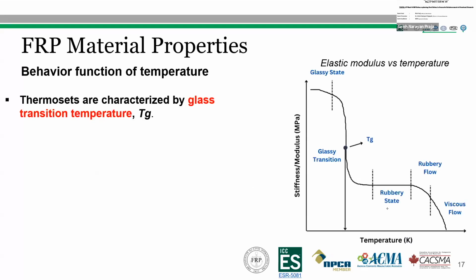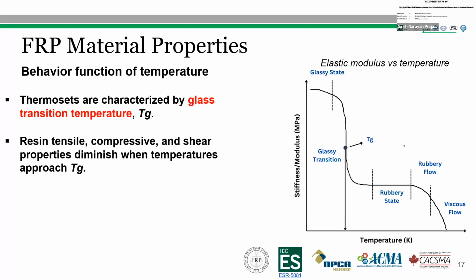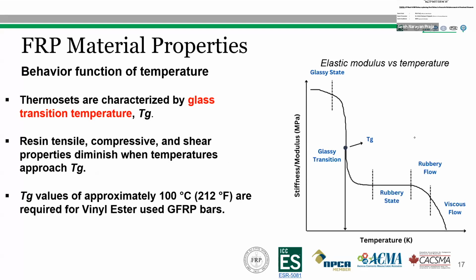The thermoset behavior is characterized by the glass transition temperature, as shown in this figure. The tensile, compressive, and shear properties of the resin decrease when the temperature approaches the glass transition temperature. A glass transition temperature of 100 degrees Celsius is required for vinyl ester, typically used in glass fiber reinforced polymer bar, and lower glass transition temperatures are generally the result of moisture absorption.